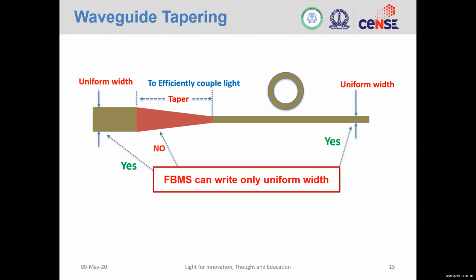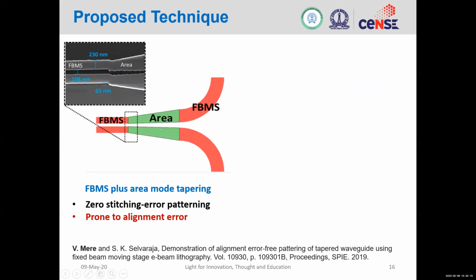So can we write this with FBMS? The answer is no. You can write this, but you cannot write this. This limitation comes from the tool; the FBMS does not allow that. To overcome this, one way is to use a combination of both FBMS and area. You write the taper using an area mode, and then you connect that. But again, the problem is that the stage drifts over time, as I have explained in the previous slide. So you'll end up with something like this, with some alignment error at the overlap region between FBMS and area.